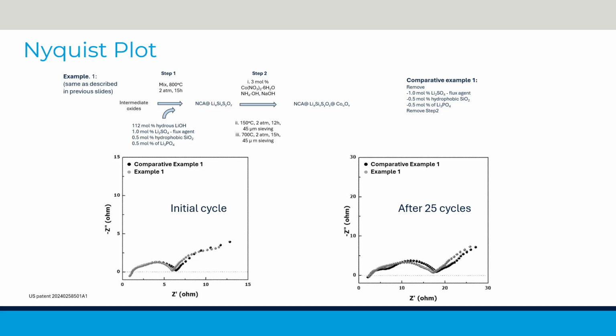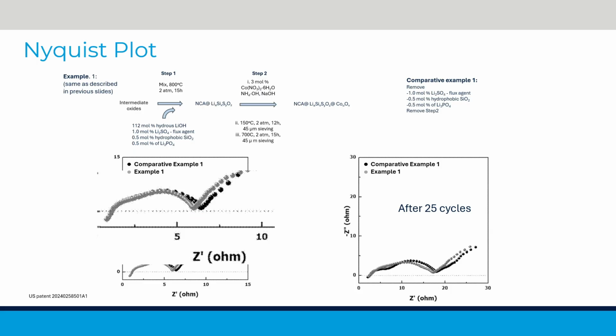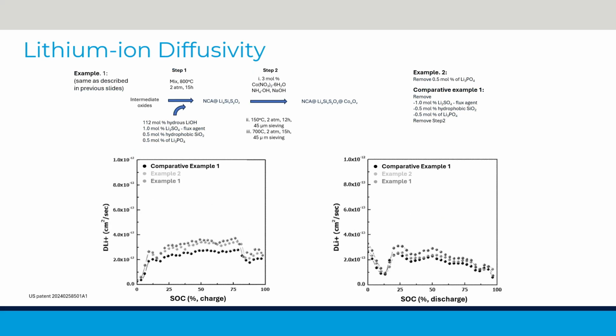For example, Nyquist plot shows that when cells are constructed in the same way, the multilayer coated NCA single particles exhibit lower interfacial resistance than that of the uncoated ones. The lithium-ion diffusivity measurement is done by using the GITT method. The conventional NCA particles without coating show the lowest diffusivity, while the particles with full coating documented in this patent show the highest. It's worth mentioning that when lithium phosphate is removed from the coating, the diffusivity decreases.